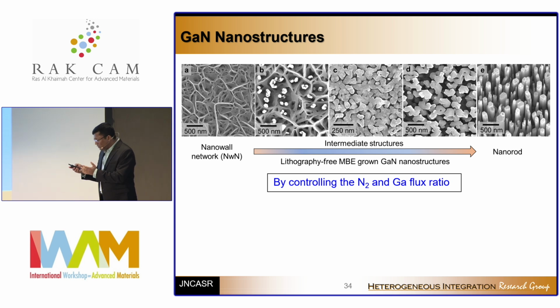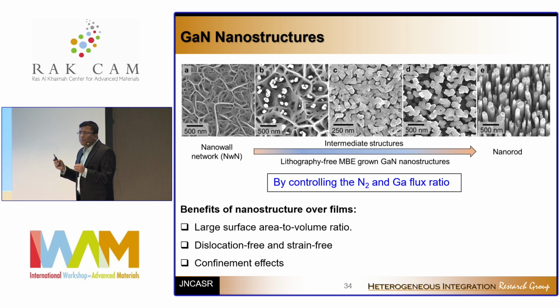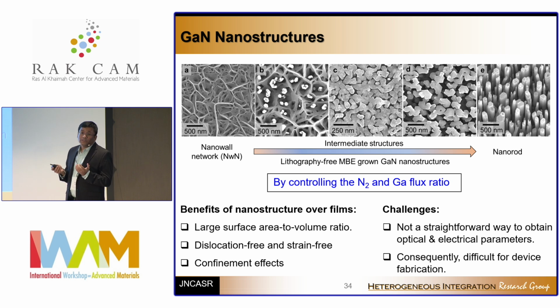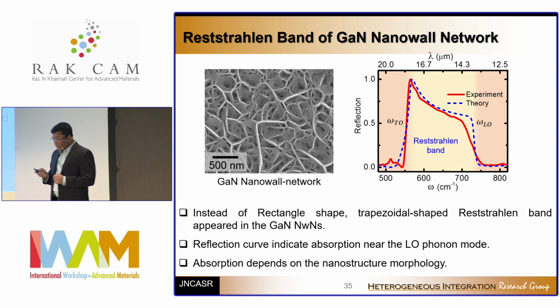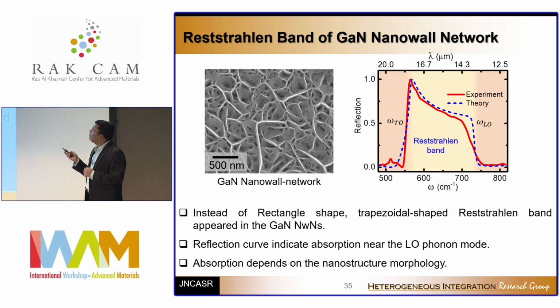And these are done for their own reasons, for different applications. But the most important part of these nanostructures is that all of them have a very high surface to volume ratio, and that has its application in many places. I'm not going there. But in the context of plasmonics or polaritonics, what is important is that if you now measure the reflection spectra of these nanowires or nano wall networks, instead of finding a rectangular shape, a theoretically well-defined reflection spectrum, you see a trapezoidal shaped reflection spectrum.